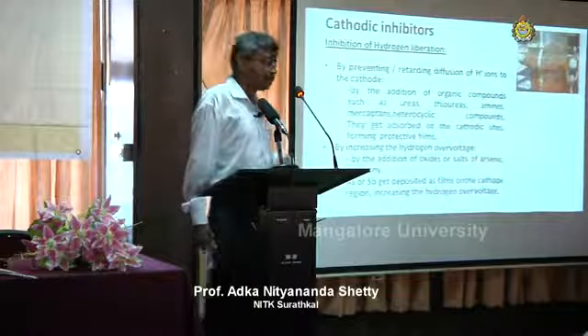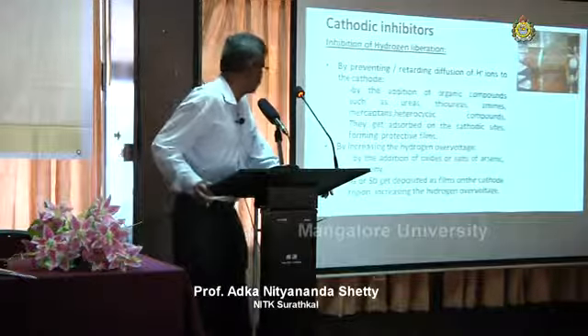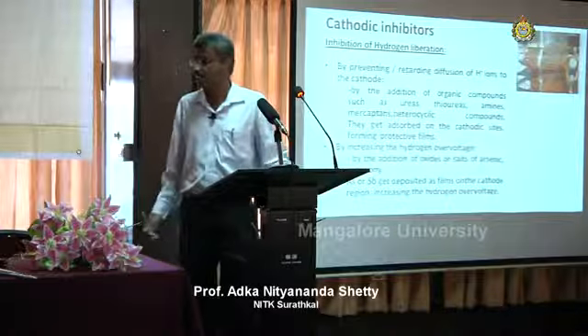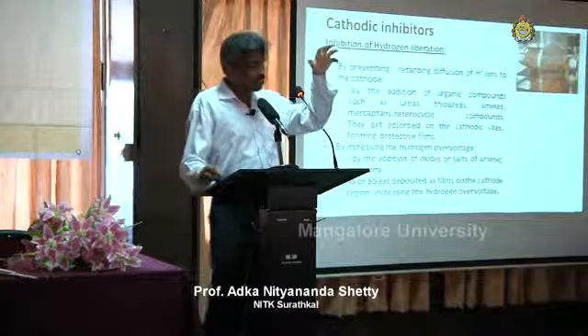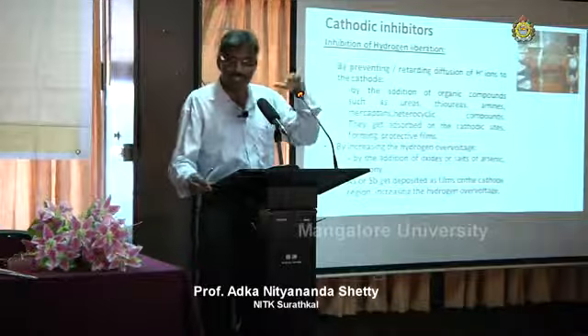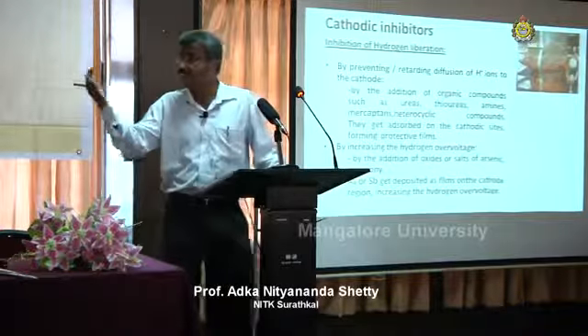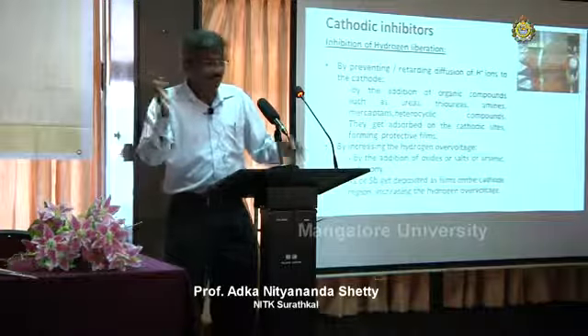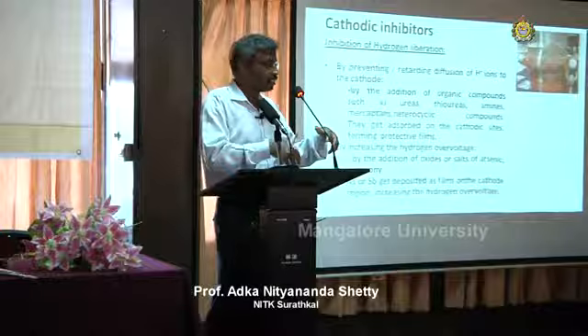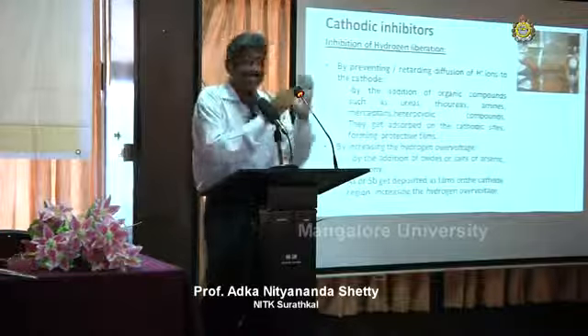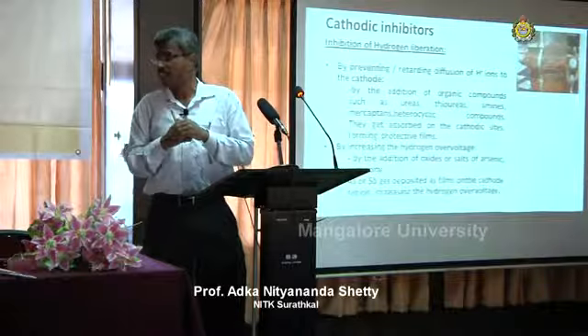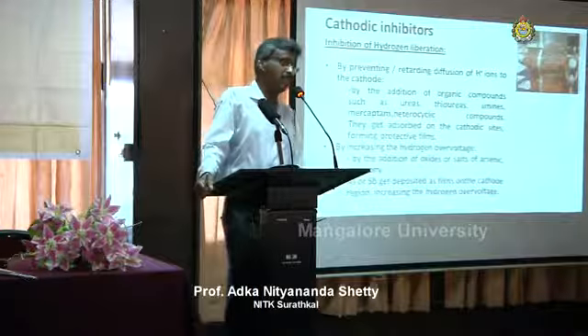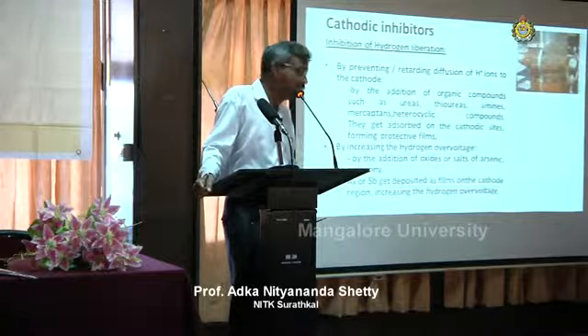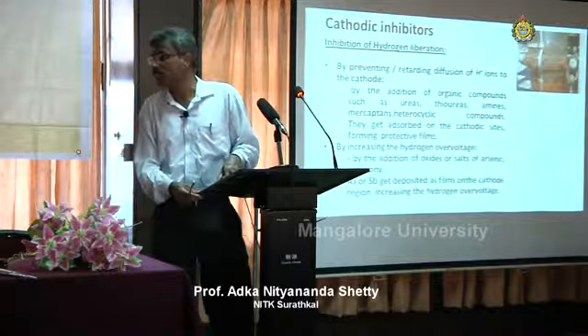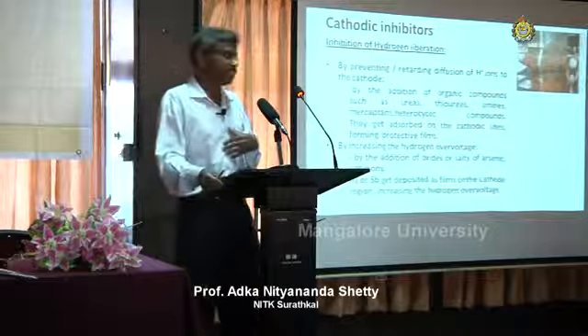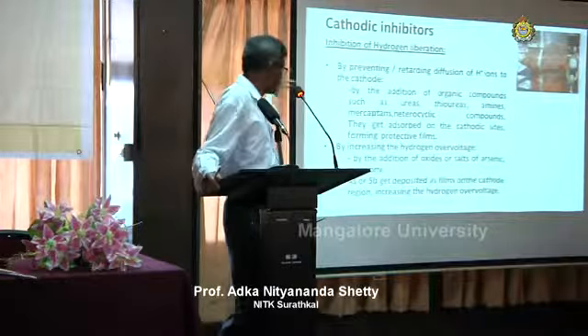Therefore, if you add compounds like oxides of arsenic, antimony, etc., these compounds will deposit on the cathodic surface as arsenic or antimony. And when the antimony or arsenic is deposited, now the cathode surface is not your metal, it is antimony or arsenic, over which the hydrogen over voltage is very high. Hydrogen doesn't get liberated easily, and therefore the liberation of hydrogen can be reduced, or the rate of liberation of hydrogen can be retarded or slowed down. Next please.